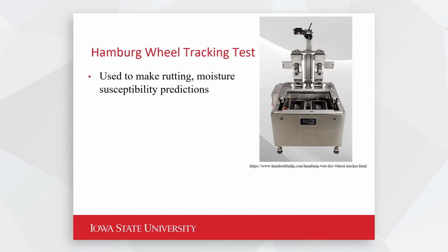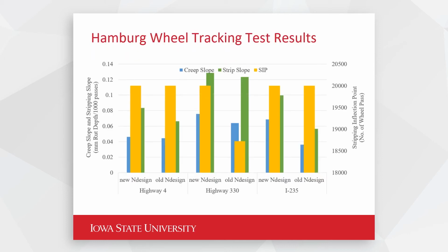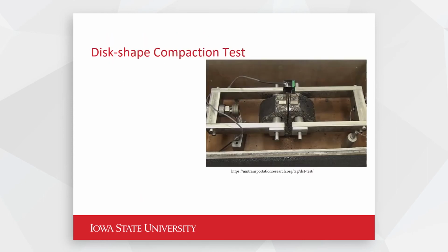The Hamburg is pretty much a standard test in Iowa. And so we look at rutting and moisture damage in the Hamburg, and we have a bar chart here. Basically, we're seeing, whether it's the stripping slope or stripping inflection point, the new design is providing equal or better performance in the new compaction criteria than the old. Okay, and so we can go to the next slide and see it.